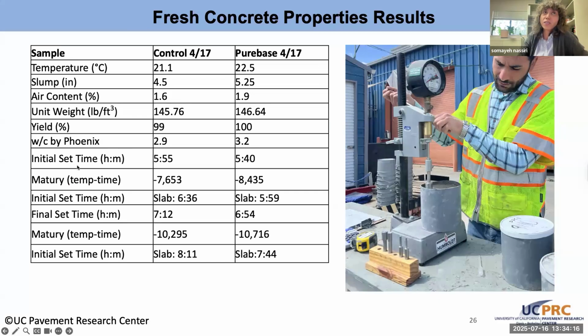These are some of the results, outcomes for our case material here, and the results of all of the fresh properties that were measured. We also measure maturity. We measure setting time with respect to maturity, and that helps us then translate the setting time onto the slab. So here are the setting times inside the slab.